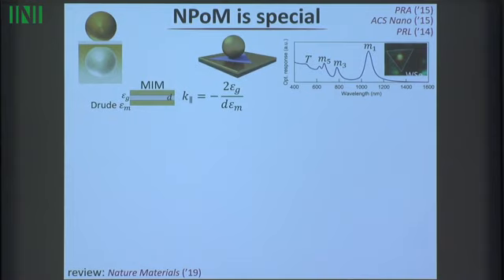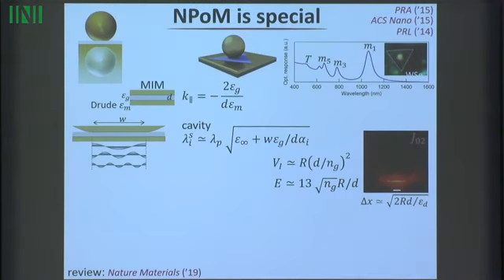In fact, as you squeeze it together, the light sits very nicely in the gap and decays off extremely rapidly into the metal. It's a bit like a coax cable which is shrunk down very small. Coax cables can happily take radio waves, even though the coax cable is much smaller than the radio wave. So it's the same mode that we're using here, shrunk down by a factor of 1,000,000 or so. We can calculate the modes that exist in there. They go very slowly, actually. Then the only other thing we realize is that there's a facet on the bottom of this particle and these edges here which reflect these modes. So I get standing wave states that sit in there, but this can be 10 nanometers long. So I can confine light into something maybe 10 nanometers long that way and less than a nanometer that way.